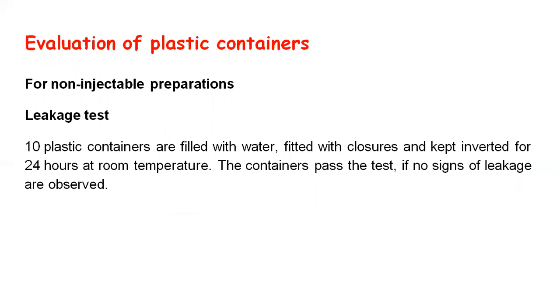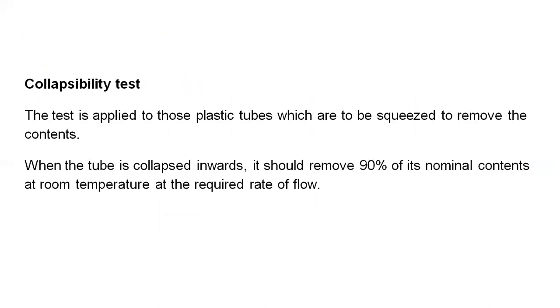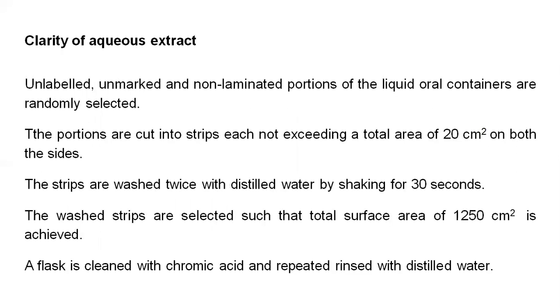Evaluation of plastic containers for non-injectable preparations. Leakage test. 10 plastic containers are filled, fitted with closures, and kept inverted for 24 hours at room temperature. The containers pass the test if no signs of leakage are observed. Collapsibility test. The test is applied to those plastic tubes which are to be squeezed to remove the contents. When the tube is collapsed inwards, it should remove 90% of its nominal contents at room temperature at the required rate of flow. Clarity of aqueous extract.